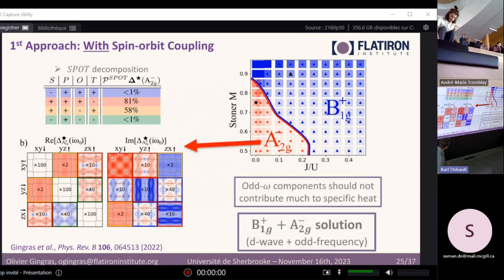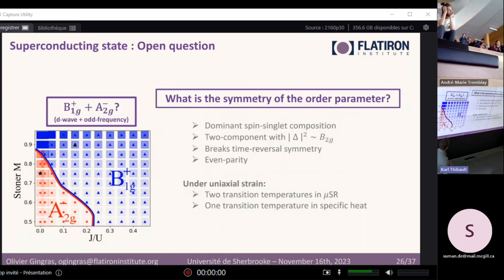And so this calculation suggests that we could actually have a state at the boundary between these two, which would be an accidental degeneracy between this spin orbit generalized D wave and spin orbit generalized odd frequency state. And so we propose this solution as the D wave plus odd frequency solution, in some sense. And so this solution, when compared with the experimental facts presented before, is dominated by spin singlets. This accidental degeneracy would be two components that would couple to the B2G shear mode. It would break time reversal symmetry and be even parity.